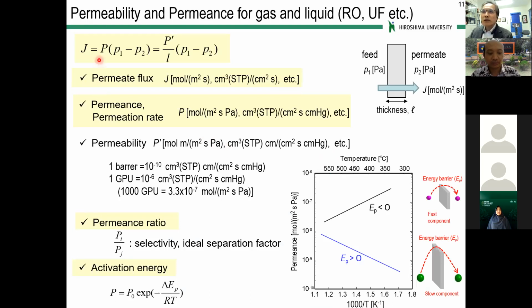Membrane performance can be evaluated with flux. Permeate flux is expressed on a mole basis or a cubic centimeter basis. Most of these units are used by polymer people, and the mole basis by inorganic researchers. The permeate flux across a membrane is given by the permeance multiplied by the pressure difference, which is the driving force for permeation of these molecules. This P is called permeance or permeation rate, with this dimension, divided by pascal, the pressure difference. And once you know the membrane thickness, you can calculate permeability, which is normalized with the thickness, okay?